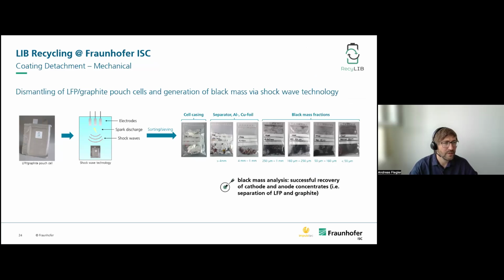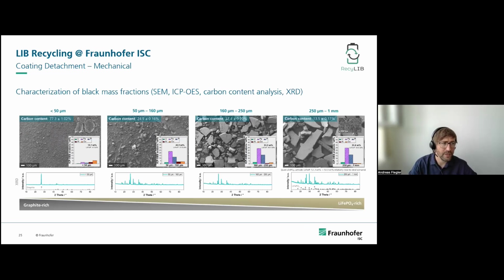Then in the first step, we receive the cell casing, then the separator and the foils, and then we have the delamination of the electrode coating, and can sieve different fractions. When we look at the different fractions in detail, we see at the smallest fraction a graphite-rich fraction. So the graphite was distributed very well in the water with these shock waves, and in the sieving step, 250 microns to 1 millimeter, we see larger particles. This is the LFP-rich fraction. So with this method, we can separate, or we can concentrate cathode and anode black masses for further steps.